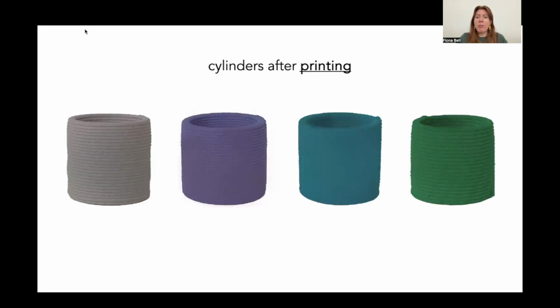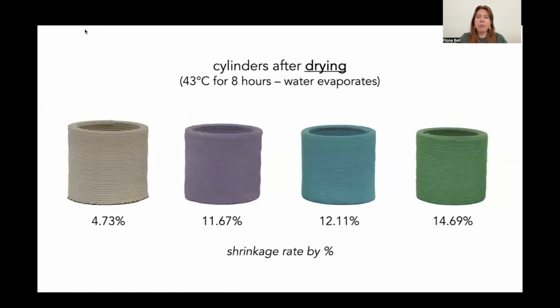We find that each recipe shrinks a different amount when they are dried and fired. To determine the shrinkage of each recipe, we 3D printed small hollow cylinders and tracked their measurements as they proceeded through each drying and firing step. The cylinders shown here are what they looked like right after 3D printing. We then dried these cylinders in a dehydrator and found that all the recipes shrank slightly due to water evaporation, with clay shrinking the least amount and all the recipes containing dough shrinking more so.